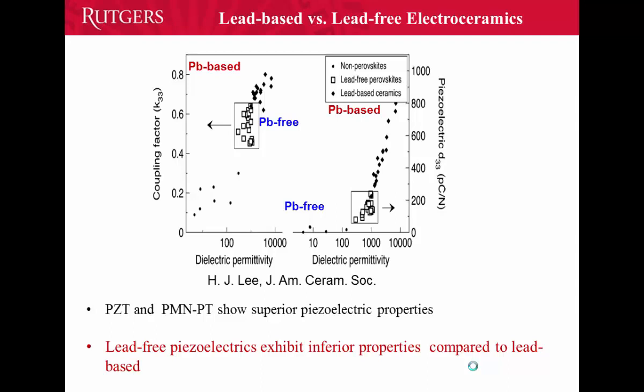The commercial ferroelectric materials are mostly lead-based compositions, because they have high ferroelectric, piezoelectric, and electromechanical properties. Here you can see that the coupling coefficient for lead-free materials is between 0.4 and 0.6. However, lead-based compositions have a very high coupling factor, up to 0.8.